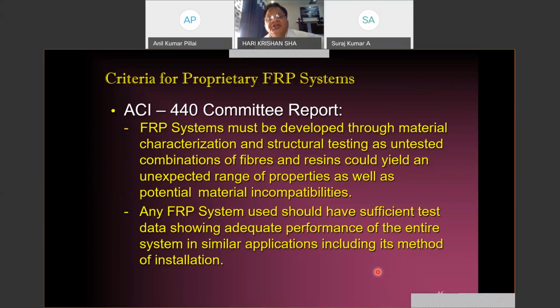You have to test the material, the fibers in conjunction with the epoxy. Fibers are not tested separately, and epoxy is not tested separately. The FRP system is basically tested in combination, where the fiber mat is covered with epoxy on both sides. So any FRP system used should have sufficient test data showing adequate performance of the entire system in similar applications, including its method of installation. These are some of the recommendations of the ACI committee, and with these recommendations, we can design a structure for the